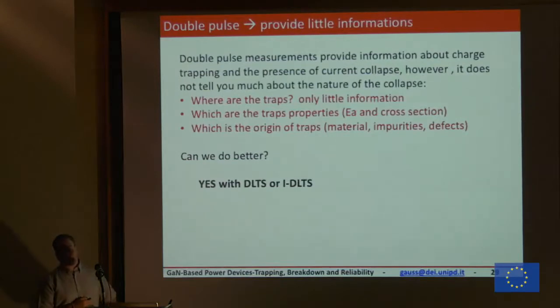Can we do better? So let's say the double pulse provides you information that there is charge trapping, we have current collapse, maybe we can say they are under the gate or not, but it tells you nothing about where really the traps are, what the nature of the traps is, what the activation energy of the traps is, the cross-section.